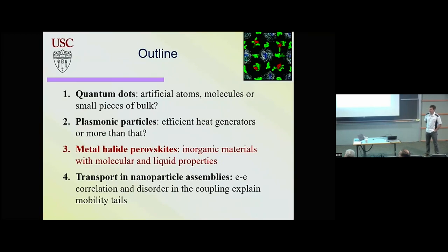So as you decrease the size of your particle, you're moving more and more into the molecular regime, which has stronger electron-hole coupling and also stronger coupling to the phonons, and so more significant polaron shifts. Yeah, if you have defects, you create local, you can have a small polaron basically. Lead dimer, it's a small polaron, like you have in TiO2.